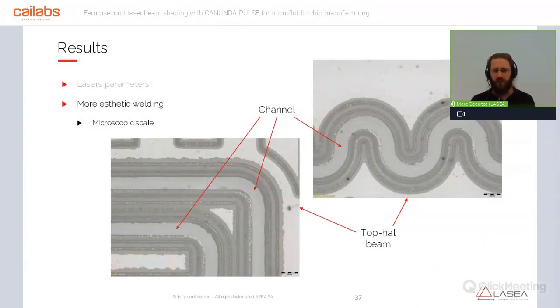And it's really interesting when we're working at the edge of a channel. Here you can observe a welding seam at the edge of a microchannel. Here you can observe the microchannel, here again, and another one here. We observe that we don't have a leak of the sample inside the microchannel, because the heating is really local. It's why channels don't collapse, and if you have biological materials inside the microchannel, they will be preserved because the heating is local.